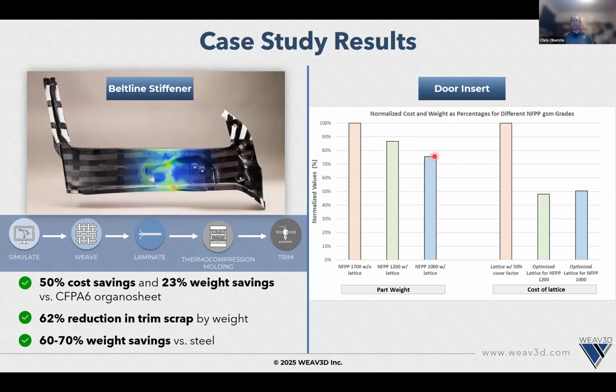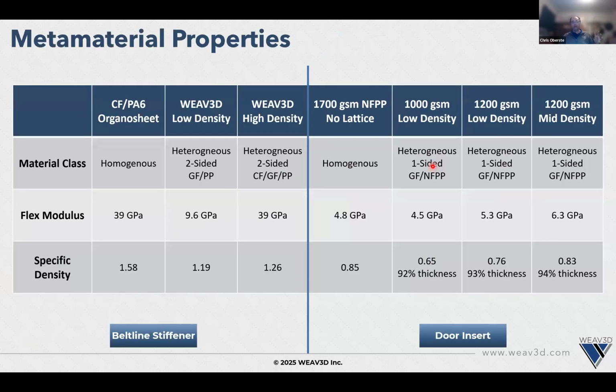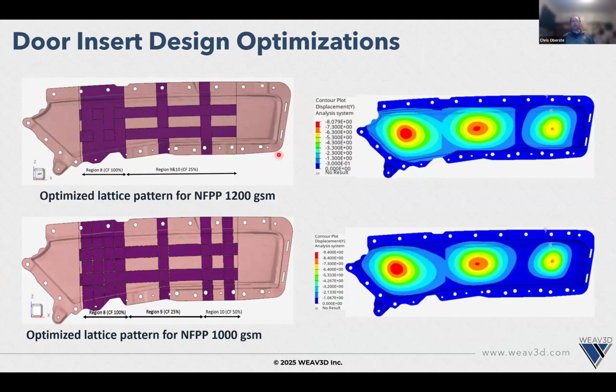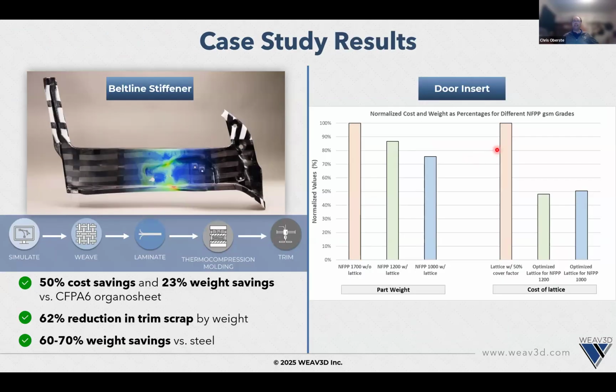And then I like to point out this one just so people can understand why you want this kind of unusual, non-symmetrical pattern on this structure. Well, if you were to just apply an evenly spaced lattice reinforcement over the entire surface, your cost factor would be about double what we're able to achieve with just putting the lattice in the particular locations where it's supposed to be. So this is really a very cost-effective approach to applying these materials, and it's leveraging that metamaterial property.